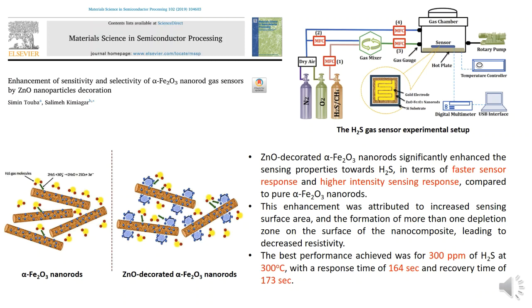As with other nanoparticles, this enhancement is attributed to the increased sensing surface area, which took advantage of the very small particle size of the nanoparticles, and the formation of more than one depletion zone on the surface of the nanocomposite, leading to decreased resistivity. The best performance achieved was for 300 ppm of hydrogen sulfide at 300 degrees Celsius, with a response time of 164 seconds and recovery time of 173 seconds.